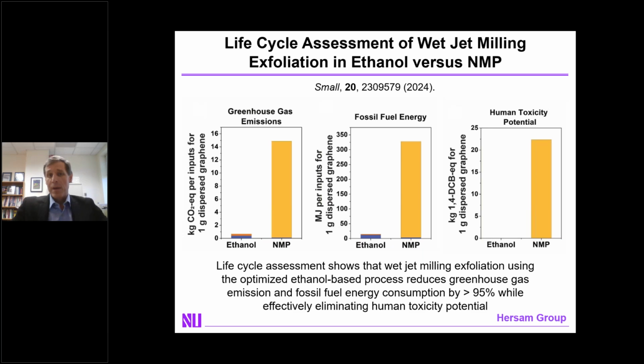In this manner, we've been able to achieve very efficient exfoliation of 2D materials in ethanol, as opposed to the incumbent N-methylpyrrolidone. And by performing life cycle assessments, we've been able to show that this wet jet milling exfoliation allows significant reductions in greenhouse gas emission and fossil fuel energy consumption, in addition to effectively eliminating the human toxicity potential of NMP. This is definitely a green and sustainable process.